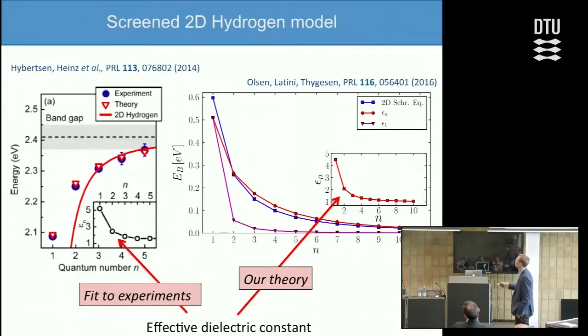So coming back to the initial example, these were the fitted values for the dielectric constant, and what we get with our model calculated ab initio is very good agreement, and therefore the exciton energies we calculate are also in very good agreement with the experiments.